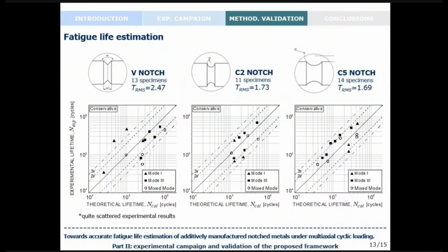In this graph, the scatter bands of 2 and 3 are shown with the dashed lines and with the dot-dashed lines, and as you can see, we obtain quite good results, especially in the case of the C2 and C5 notch specimens, since all the results are at least within the scatter band 3. Whereas in the case of the V-notch specimens, we have some outliers, 2 here and 1 here. This is also due to quite scattered experimental results that we obtained during the fatigue tests. But we still have quite good results, as highlighted by the TRMS values. It is likely higher than the case of C2 and C5 notches, which is instead very good and similar to each other.